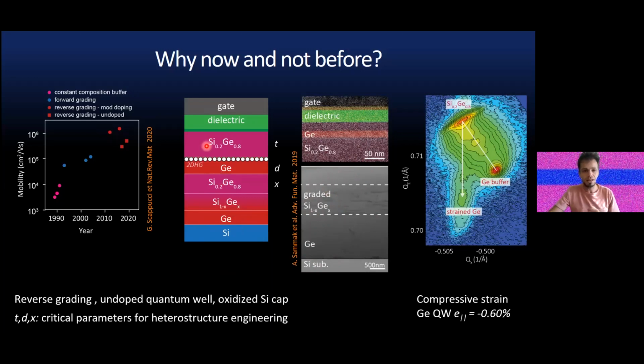Then you grow your quantum well. And the next enabler was to actually get rid of modulation doping to put charge into the quantum well. And here really was our contribution: to try to do reverse grading and get rid of modulation doping and see where we would get. And in this heterostructure, really there are three key parameters I want to highlight. This is the percentage of germanium in the virtual substrate, which sets the lattice parameter, and in turn it sets the strain, and therefore a lot of the band structure parameters. The thickness of the quantum well, and very important, the separation of the quantum well from the dielectric interface.